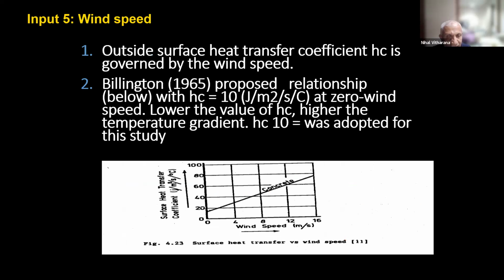Wind speed, as I said, is very important because we lose heat due to convection. At zero wind speed, HC, the heat transfer coefficient, is about 10, but when it is windy, I think it's about 16. It's very sensitive, it goes up quite a lot. So if it is windy, our temperature would be much lower because we lose heat from the wall to the surroundings.